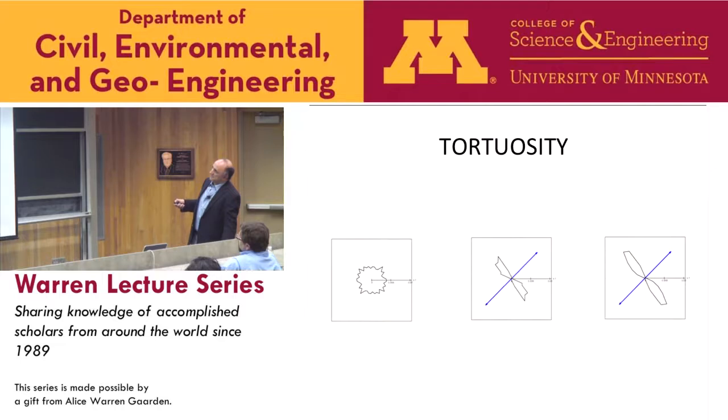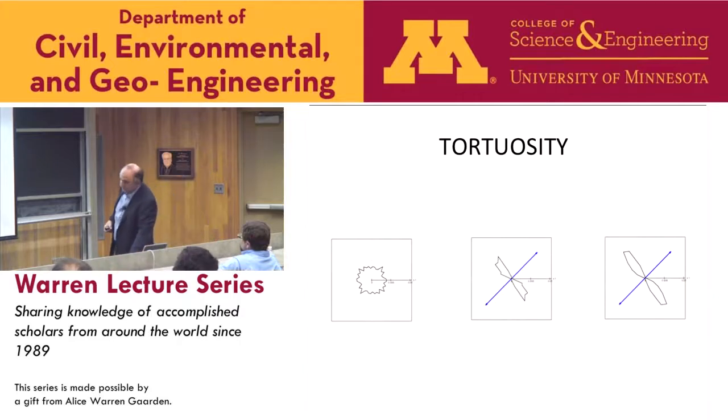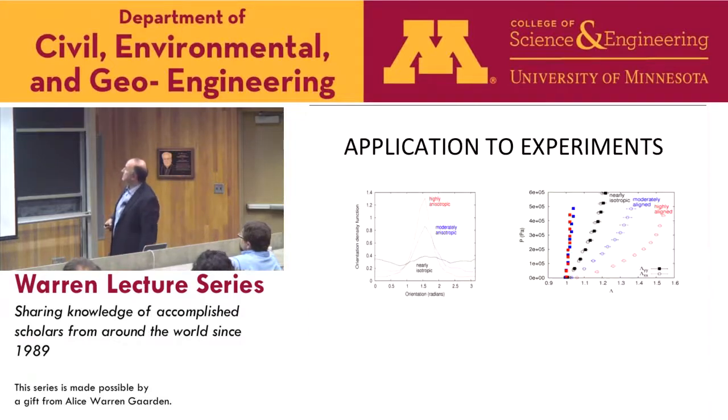There is increase in tortuosity in the direction perpendicular to the stretching. What this means is that the fibers not only do not straighten in the direction perpendicular to the maximum principal stretch, but they actually become tortuous, buckling, right? You have buckling and tortuosity. The fibers don't become straight, right?